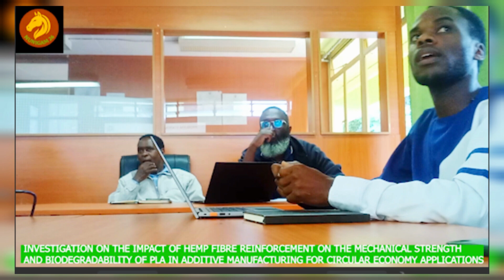For the soil burial method, we shall put our sample in soil for 6 to 90 days. For industrial composting, we shall expose it to a temperature of 50 to 60 and humidity of 40 to 60, under controlled parameters so that we can see if the weight will be reduced or other parameters. Also, we shall do that analysis.